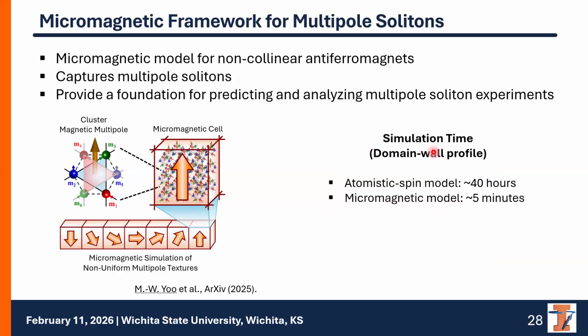Also, this micromagnetic model is much more efficient than the conventional atomistic spin model. So for example, in the case of the previous simulations, it takes about a few minutes for the simulation, but it would take more than tens of hours if we used an atomistic spin model. So this micromagnetic model can provide a foundation for predicting and analyzing multiple soliton dynamics before and after the experiments.